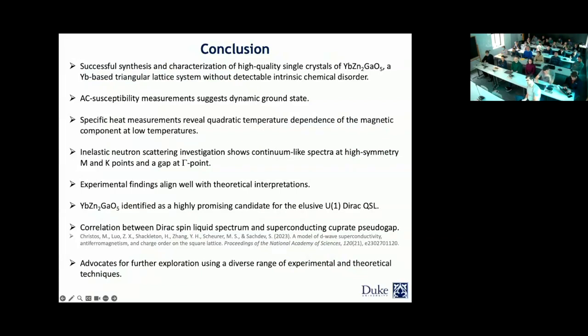One other thing I would like to mention about the inelastic neutron experiment is that in the previous 1114 compound, when it was proposed as a spinon Fermi surface, they had excitations all across the Brillouin zone. In our case, when we looked at the data, you can see that there's clearly a pickup at the K point, and there's a gap opening at the gamma point. That would be more indication that you have Dirac cones and not a spinon Fermi surface. And then we have identified this as a U(1) Dirac quantum spin liquid candidate.